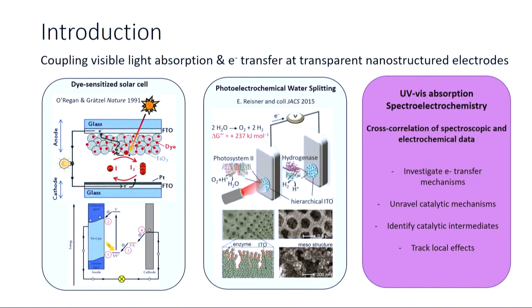One is the dye-sensitized solar cell that was initially developed by O'Regan and Grätzel. And basically the principle here is that you have a transparent nanostructured electrode, which is made of semiconductive titanium dioxide nanoparticles, and they are functionalized by a dye. And upon proper band alignment and potential alignment, what's happening is that when you shed light on the dye, then you trigger electron transfer, and this drives a photocurrent.